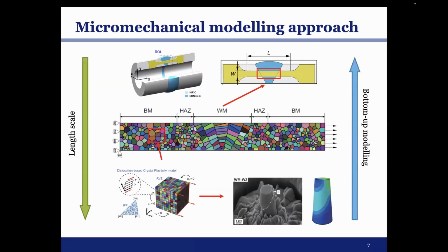So to model this behavior, we propose such a micro-mechanical modeling approach. So firstly, we construct such a representative microstructure model according to some careful microstructure characterization. And then we use a crystal plasticity model to describe the elastoplastic behavior of the grains. And then we need to calibrate the models. So we use two kinds of ways. One is to do just simple tension of these simplified polycrystal aggregates, and we fit the experiment data that we obtain for each region from the tensile test. And additionally, we do compression micropillar tests to further confirm our parameter calibration. I think we can use such a model to study different behaviors of this weldment.